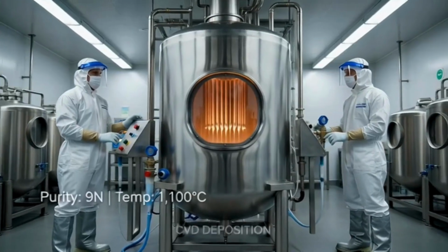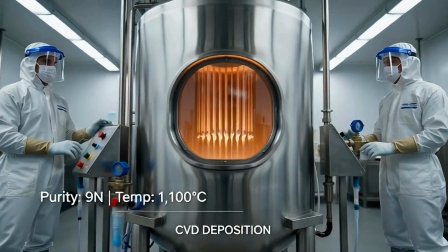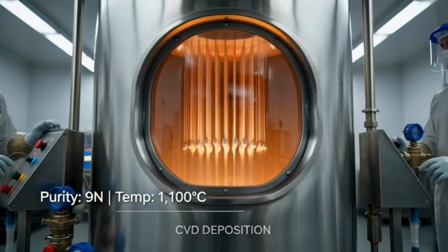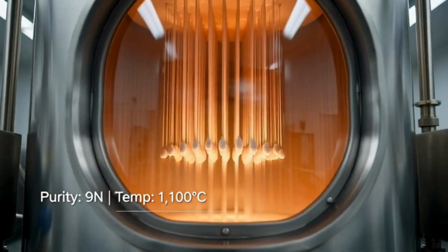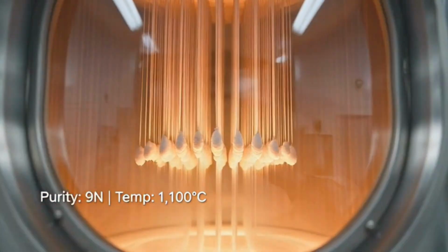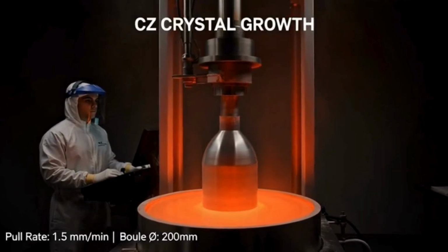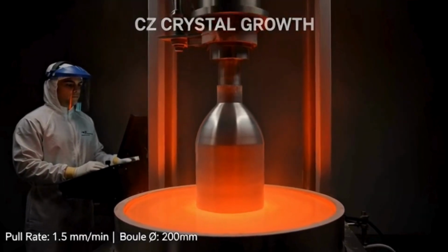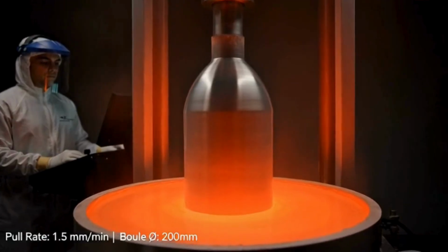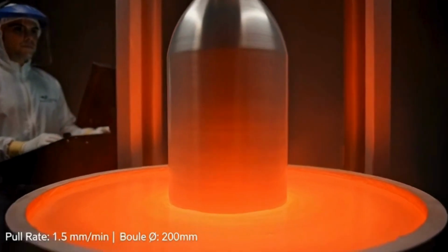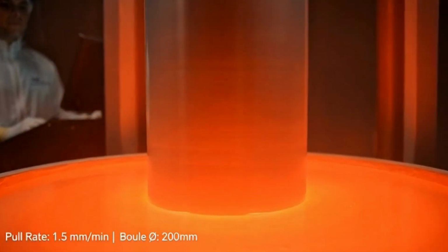Inside CVD reactors, chemical vapor deposition builds ultra-pure silicon onto seed rods. The result is polysilicon, 9 nines pure, the cleanest form of silicon on Earth. A seed crystal is drawn upward from molten silicon at precisely 1,414 degrees. Atom by atom, a single crystal silicon ingot, called a boule, forms in perfect alignment.